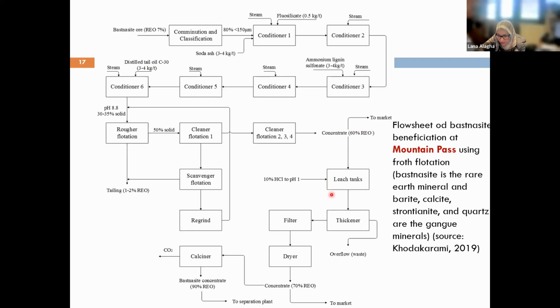using HCl at pH 1 to dissolve the carbonate minerals. And then the product goes to a thickener for solid-liquid separation, and then filtration and drying, and then at the end you'll have a concentrate averaging 70% of total rare earth oxides. That goes for shipping for production.